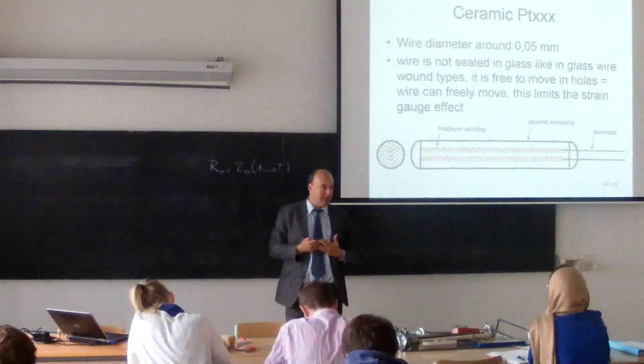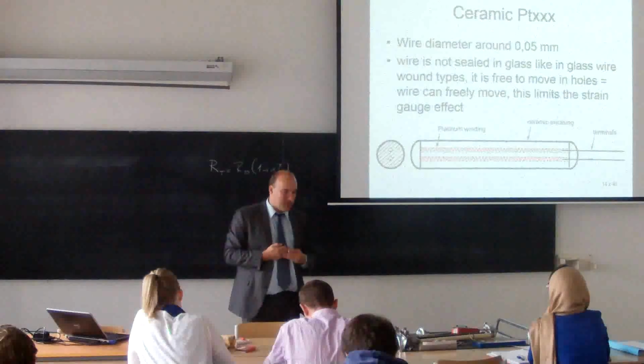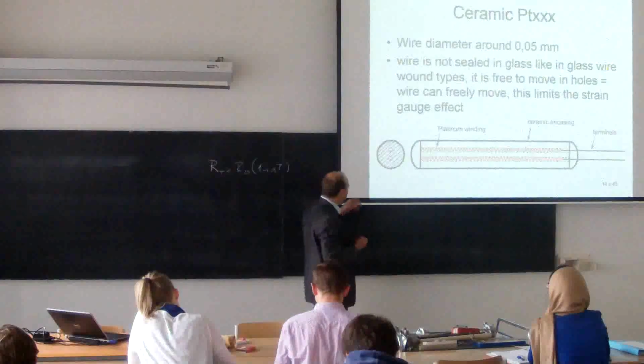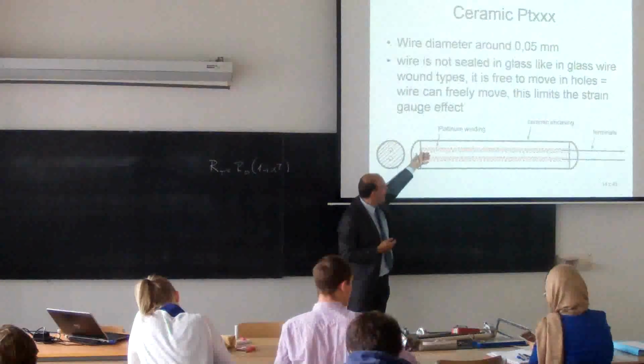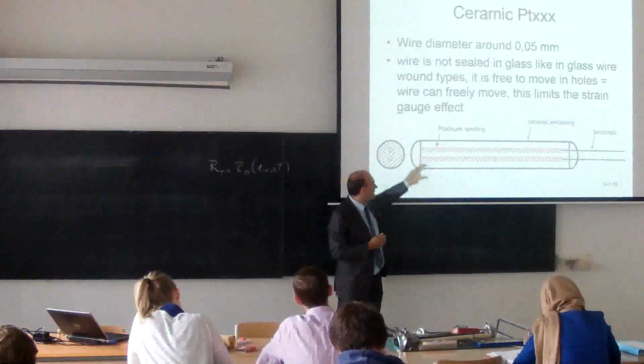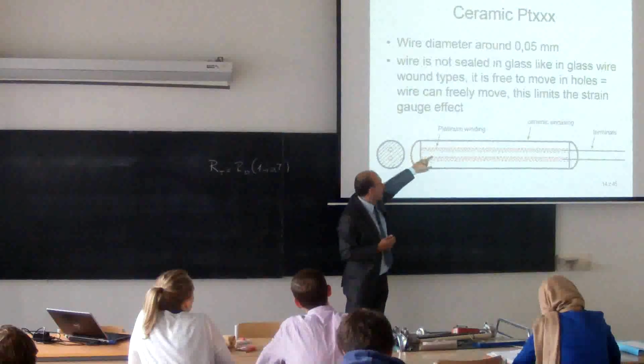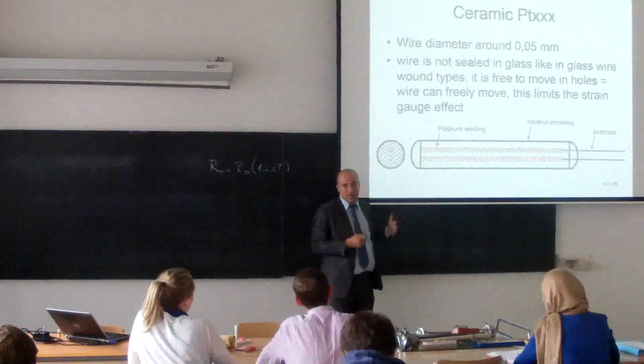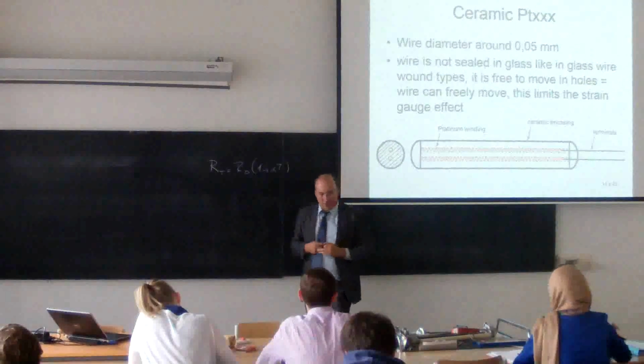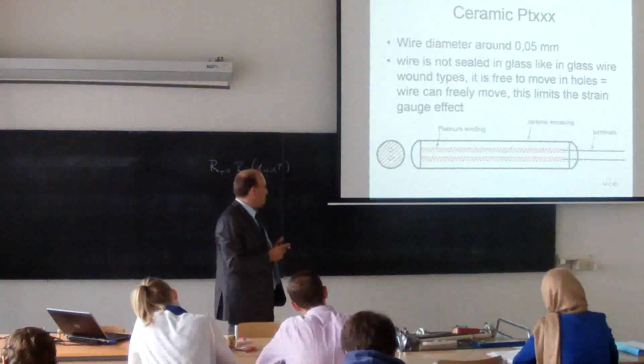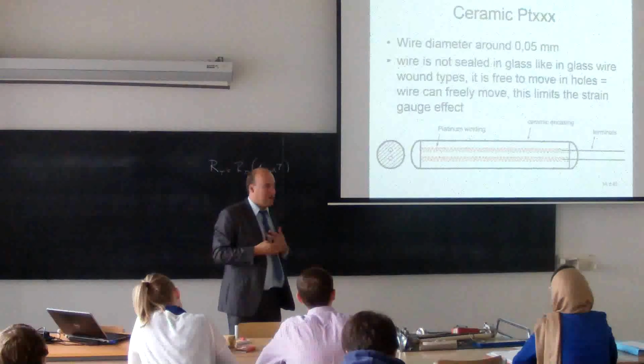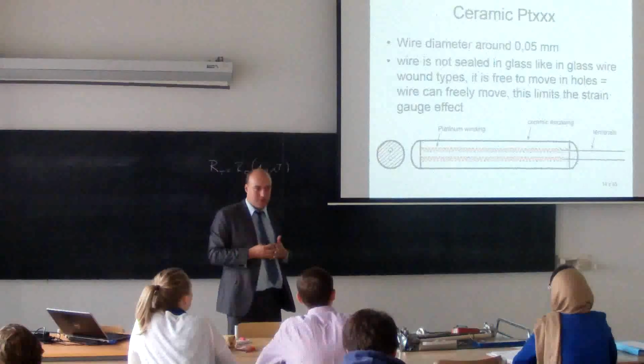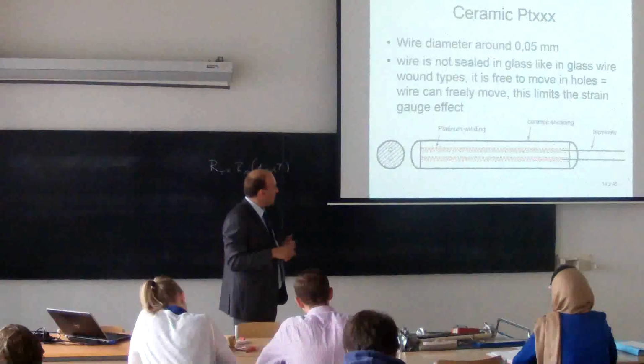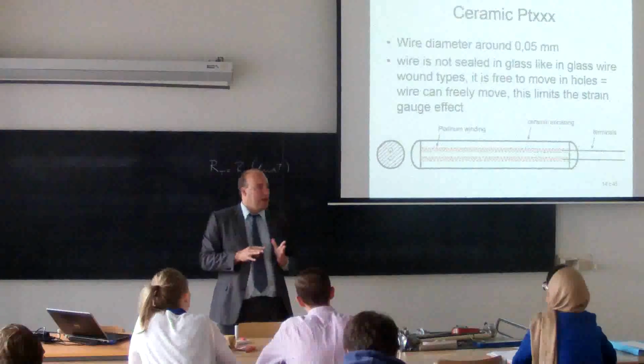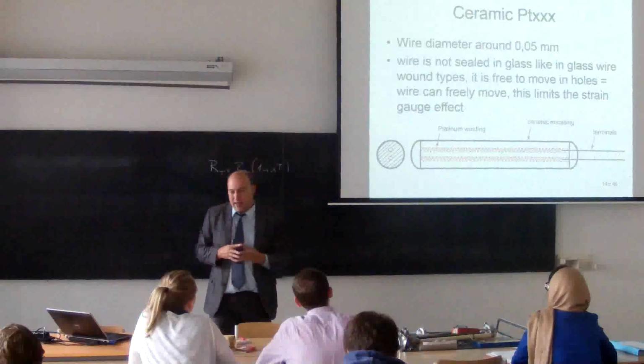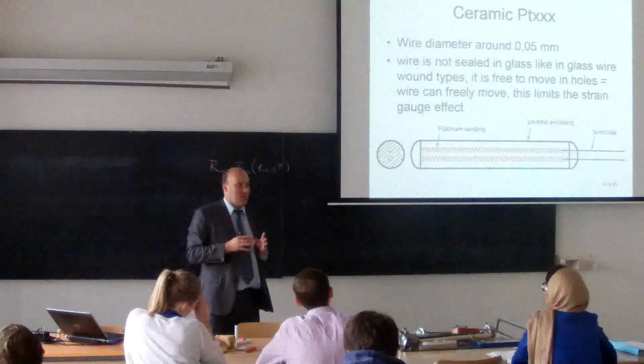So it's free to move inside. So for this version, we don't have such a problem with the strain gauge effect. Even if the coefficient of thermal expansion of the ceramics and the platinum wire is different, it doesn't matter. Because if I change the temperature, this will expand, this will expand. The platinum wire is free to move inside the holes. Plus, the temperature resistivity of the ceramics is better than for glass, so we can hold for higher temperatures. So typically, this platinum ceramic sensor can work up to 850 centigrade. So a little bit more than the glass version. The price is approximately the same.